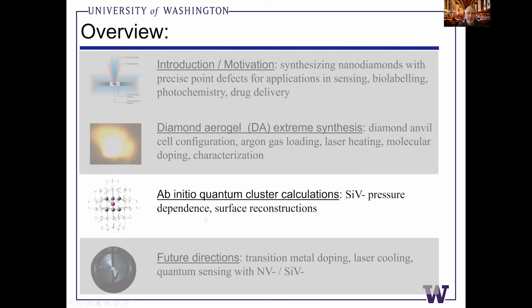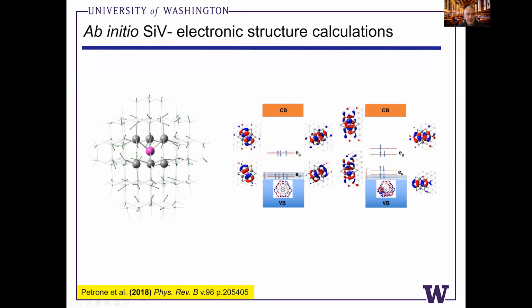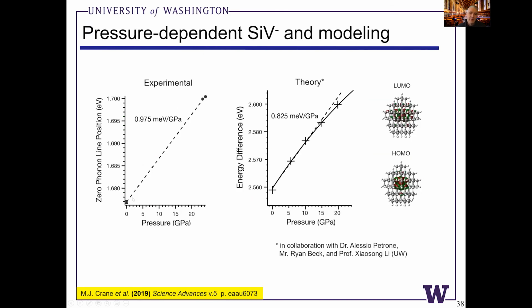So still an interesting question, but a really surprising, counterintuitive discovery that argon is not chemically inert. It dopes the diamonds. So I also wanted to share some really nice calculations that Xiaosong's group led in terms of studying the optical transitions of the silicon split vacancy as a function of pressure. This PhysRev B paper is a great description of the different electronic mid-gap states of the negatively charged silicon split vacancy. So our group collaborated with Xiaosong effectively. We made high pressure measurements of the zero-phonon line, ZPL, of the split vacancy. And this is double blind. We didn't share our results with Xiaosong's lab.